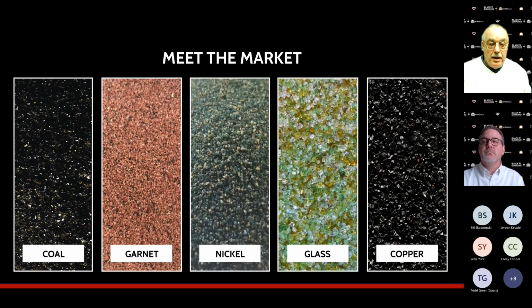If I may, Aaron, one comment on these abrasives is that even within the same family of abrasives, they're not all created equal. For example, coal slag is derived from coal-fired power plants predominantly, and what type of coal they used in that plant will affect the properties of the coal slag abrasive. That is, if it's soft, say bituminous, low sulfur coal from the northern slopes, that doesn't make a very good abrasive because it's soft and dusty, and will have those kinds of qualities when you try to blast a surface. On the other hand, the anthracite, or the higher BTU, the harder coal, although higher generally in sulfur, is still a better abrasive, and it's harder. It has less dust characteristics, and so all coal slag is not created equal.